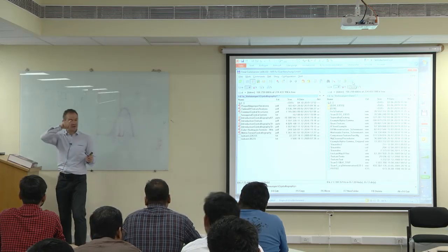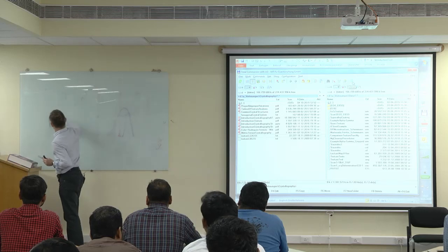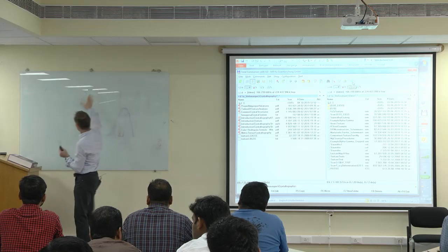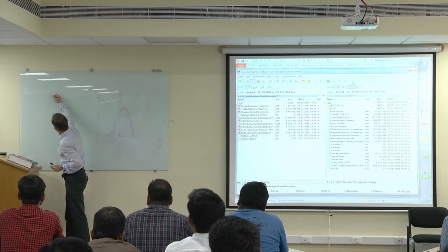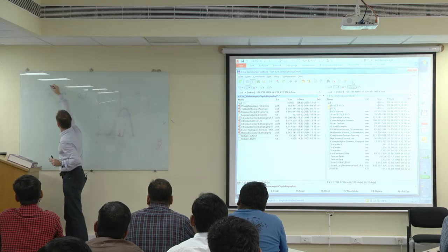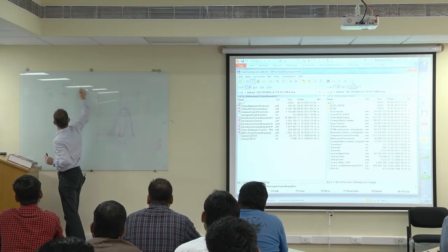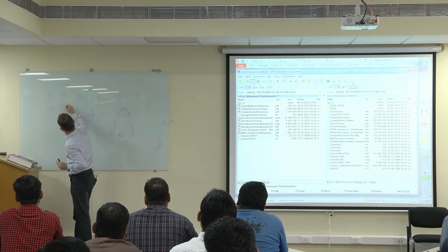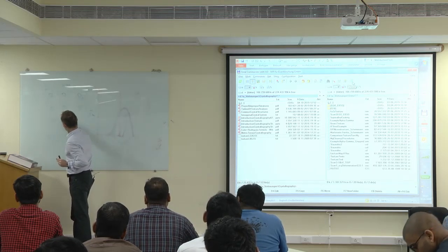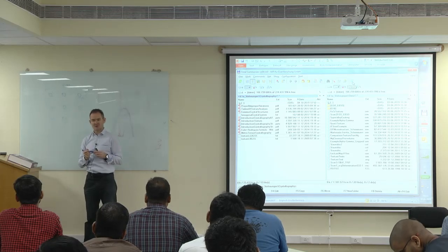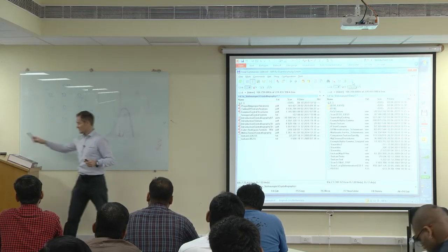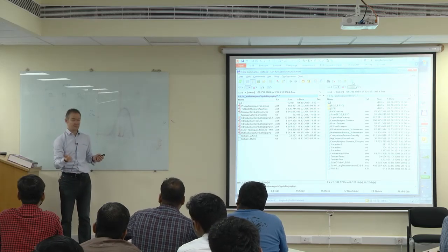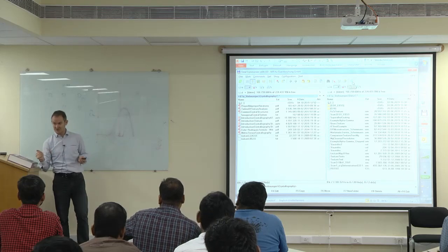And what we do, and that was what I explained earlier this morning, we have developed software which, if you want to measure a very accurate texture, you make lots of little maps distributed over a maybe several centimeter large area, regularly distributed, and you add them all together. Then you can be quite sure that your texture is right. And we see then it becomes much more accurate and much more informative than any kind of X-ray measured texture.